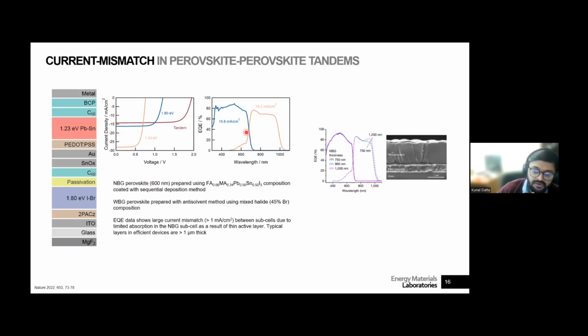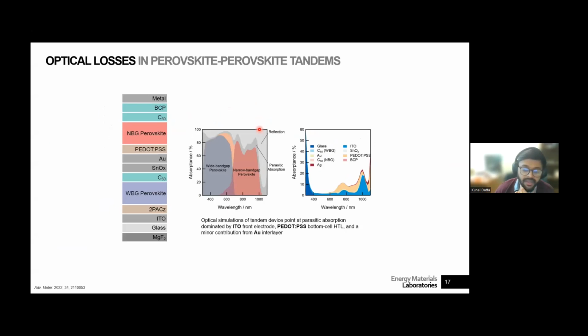And that's a bit different than what is elsewhere in the field, because if you look at this SEM image from this paper, which came out, I think, in 2022, the narrow bandgap cell is over a micron thick, 1200 nanometers even. And that really allows the EQE to go up significantly, right? But with our processing at that time, with this two-step process, we couldn't manage to do that. So we had to find a different way to improve the current in our device. So again, we went to optical simulations, and this is again a simulated spectrum. So the wide bandgap, the narrow bandgap, the parasitic absorption, the reflection, and the overlap.